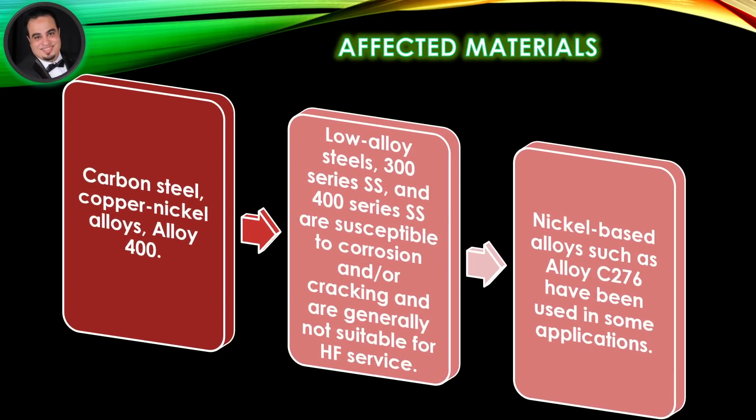Affected materials: Carbon steel, copper-nickel alloys, Alloy 400, low-alloy steels, 300-series and 400-series stainless steel are susceptible to corrosion and/or cracking, and are generally not suitable for hydrofluoric service. Nickel-based alloys such as Alloy C276 have been used in some applications.